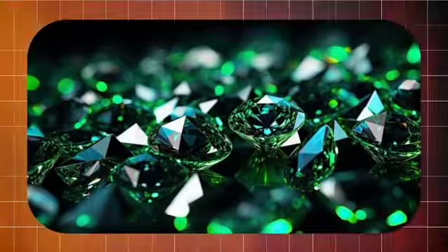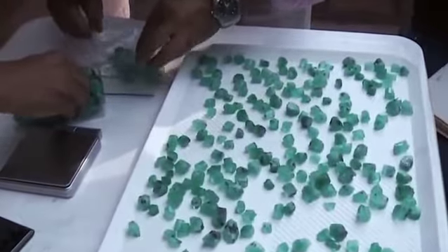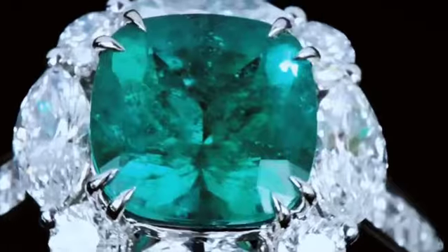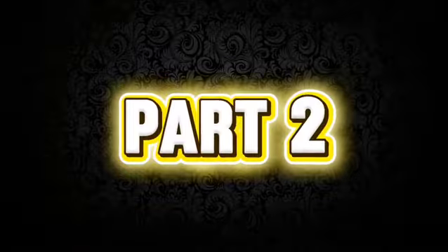Green diamonds. The color here is derived from natural radiation. Alpha particles from nearby uranium or thorium-containing rocks displace carbon atoms near the diamond's surface, creating a thin green layer. This is a surface-level effect, which is why a truly saturated, all-natural, fancy vivid green is one of the biggest prizes for a collector.